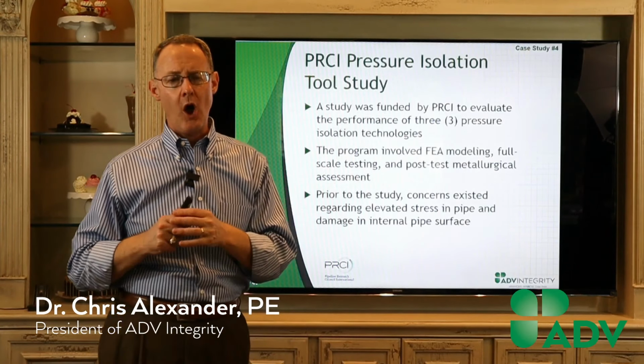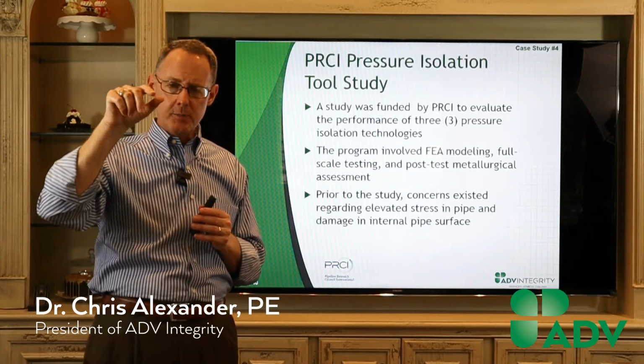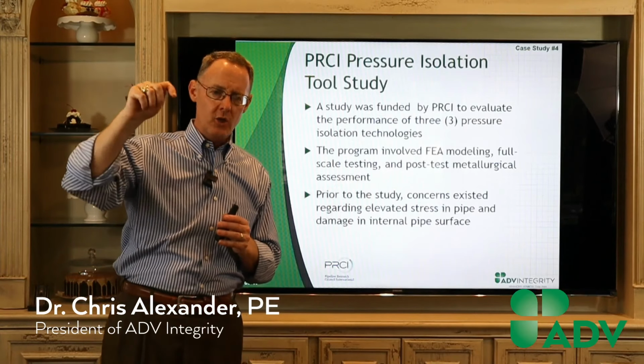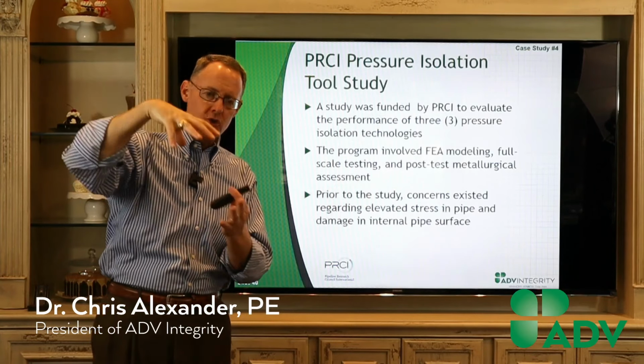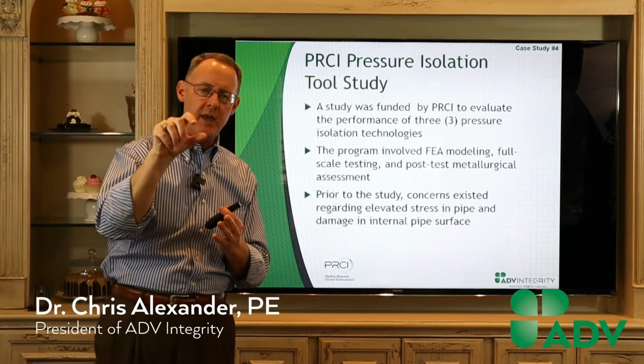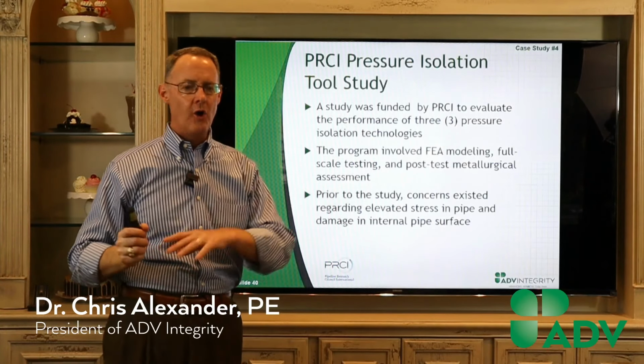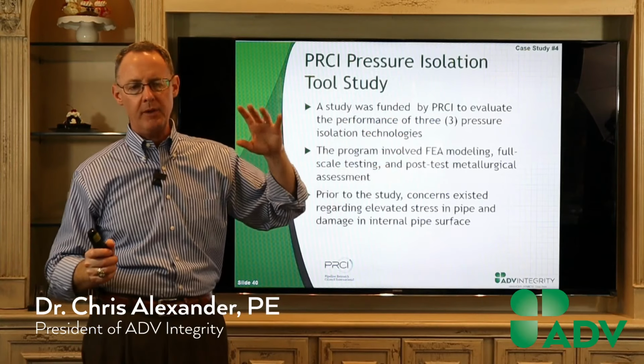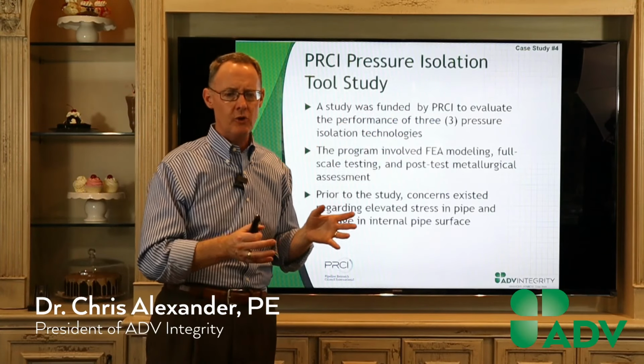Now, offshore, this technology is used quite a bit, but the difference between onshore and offshore is that offshore pipelines tend to be thicker, especially deep water pipelines, because you've got a very high level of external pressure, so you make the wall thick so that it doesn't collapse. Onshore, we don't have to worry about that. These pipelines are buried, but you're not seeing a lot of external pressure.